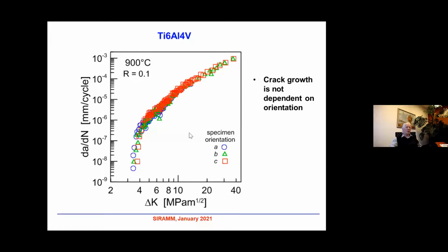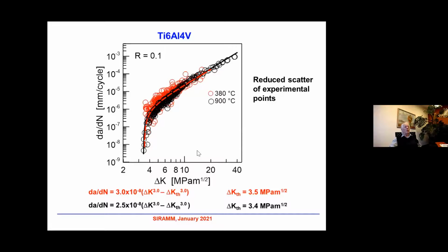We again measured the crack propagation curve, which is the dependence of crack growth rate on the stress intensity factor range. And what we can see is that all orientations A, B, and C lie on one curve. The scatter is relatively small, like in conventional materials. If we compare the data at 380 and 900, this curve can be fitted quite well with these two curves, and the threshold value, the value below which the long crack does not propagate, is 3.5 megapascal meter to 1/2 for 380, and practically the same for 900. So here is only reduced scatter of experimental data.